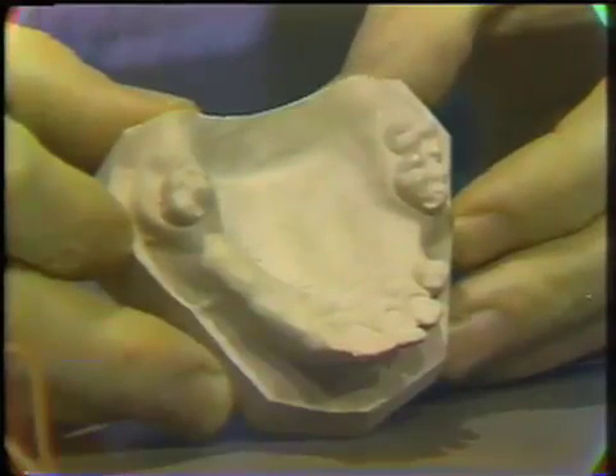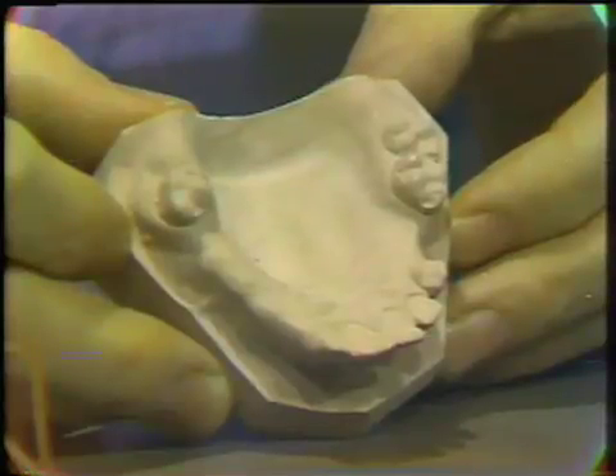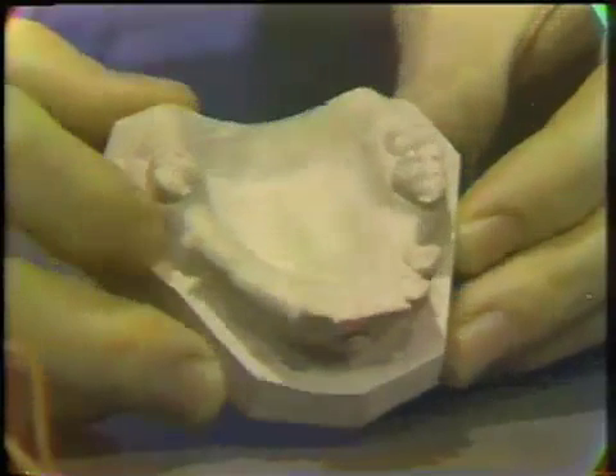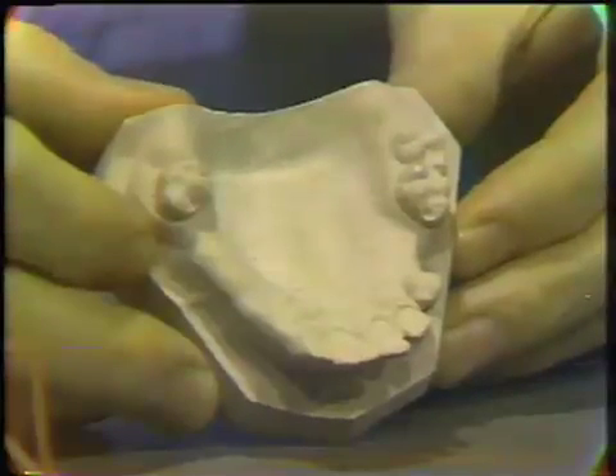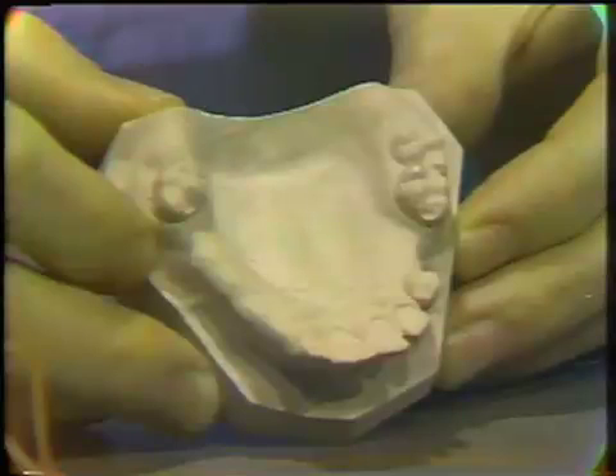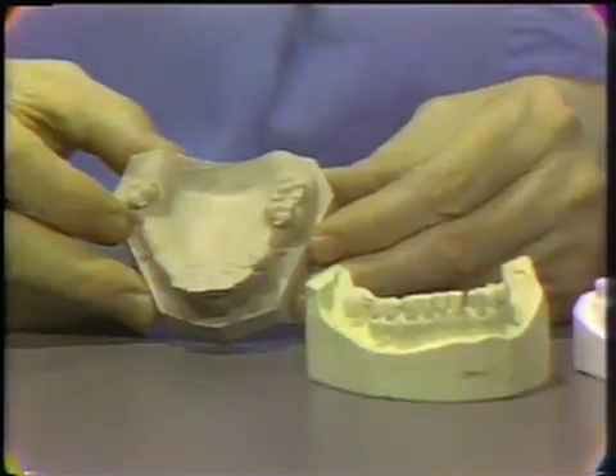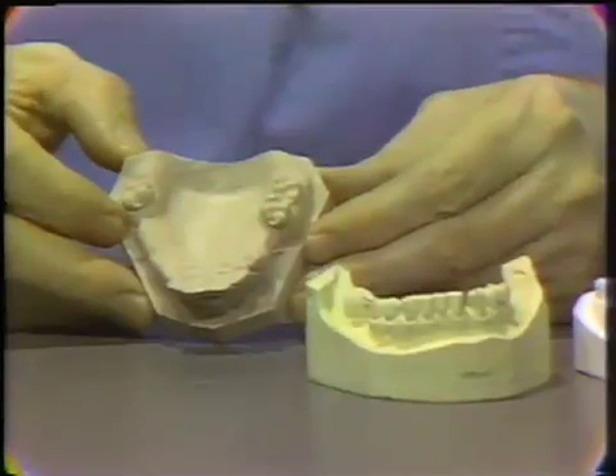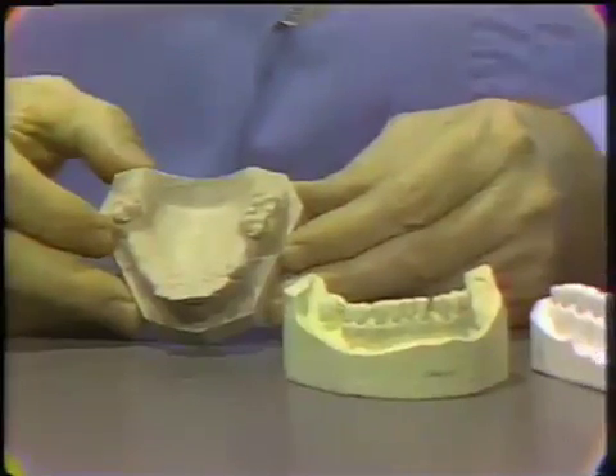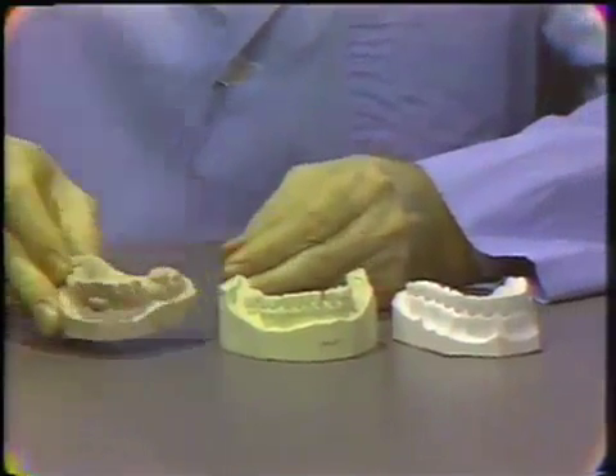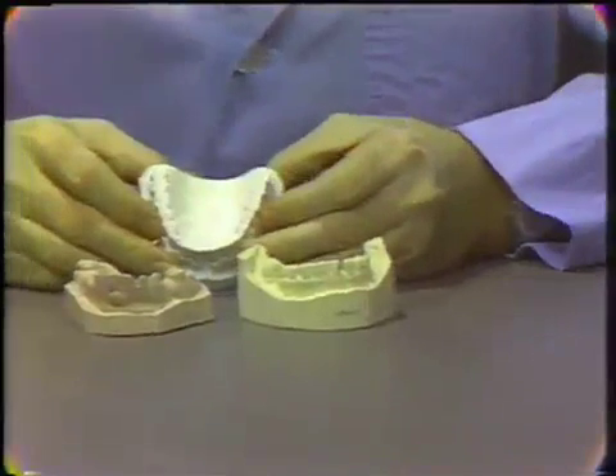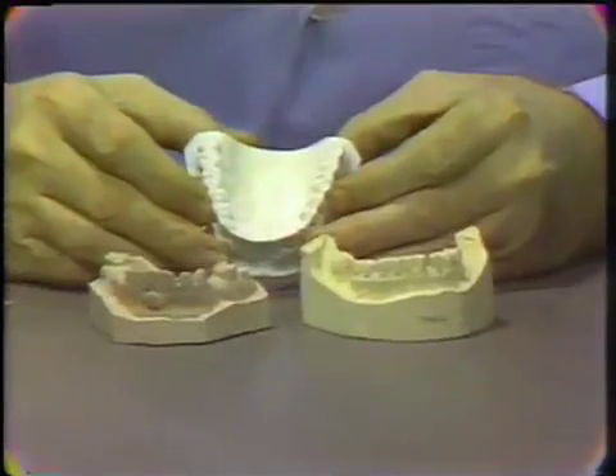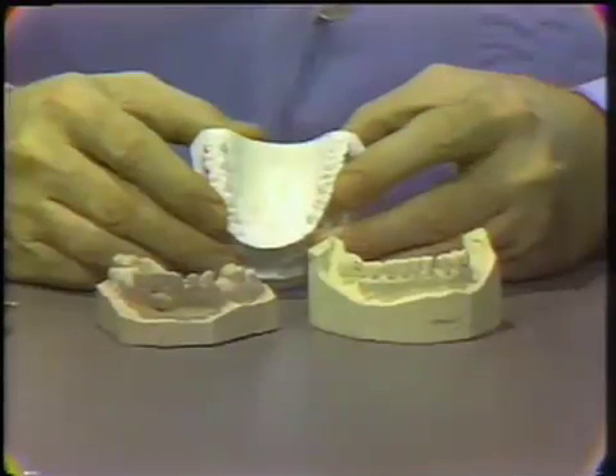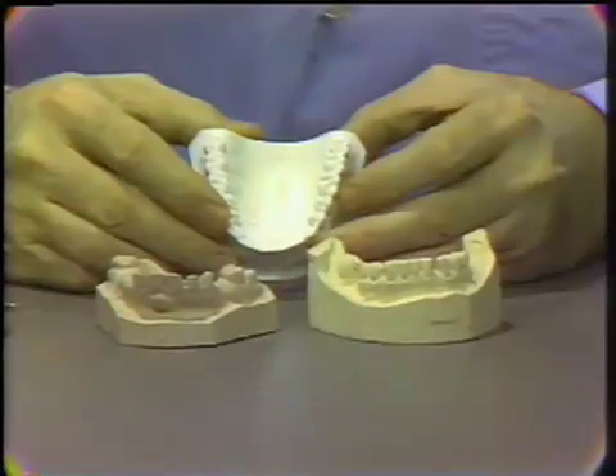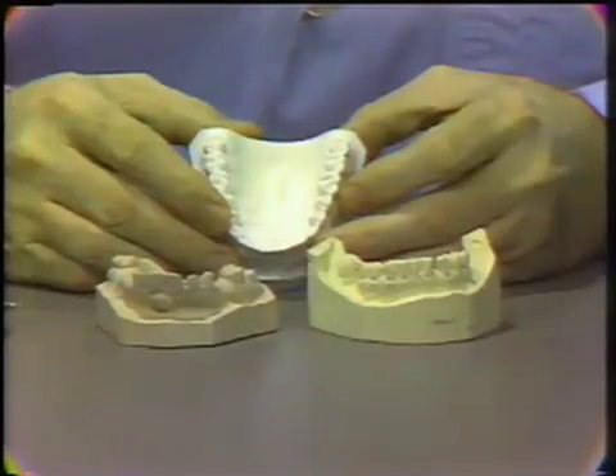If you use dental stone, you can mix 100 grams of dental stone with as little as 30 milliliters of water. And with this model that I have here of improved dental stone, you can use as low as 22 to 24 milliliters of water for 100 grams of powder. Since in the reaction of the gypsum material with water, approximately 19 milliliters of water is required per 100 grams of powder, you can see that considerable excess water is used in the mixing of the model plaster. As a result of this, you'll find that the strength of these materials is in the order of model plaster being the weakest, then followed by regular stone, and followed by improved stone.